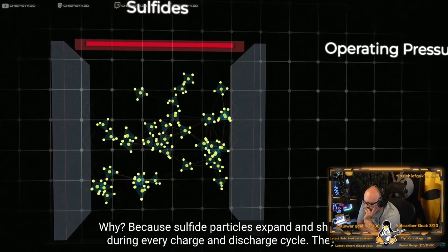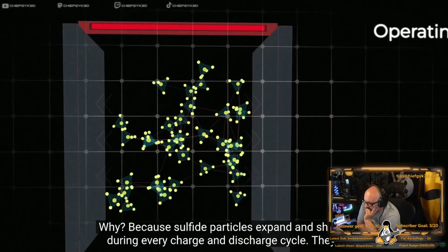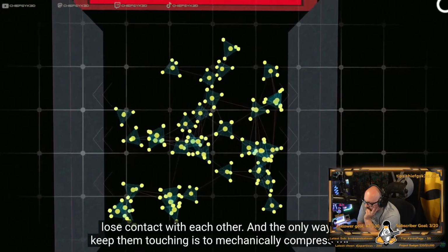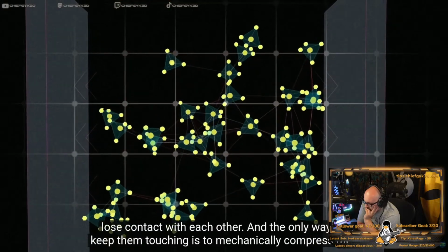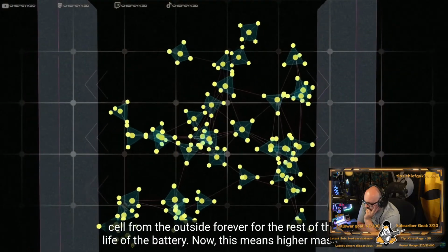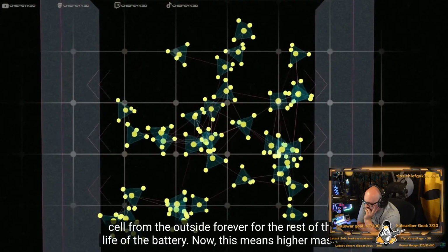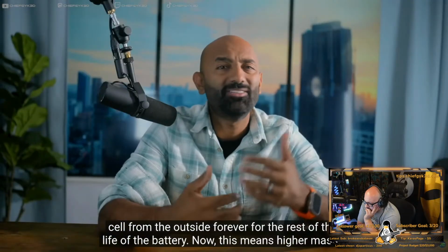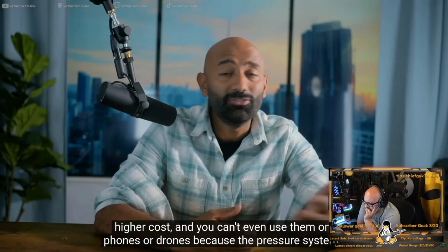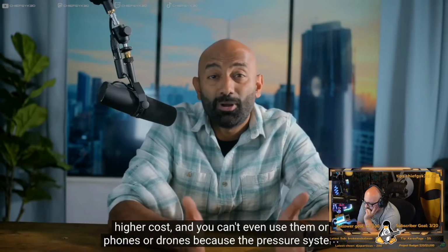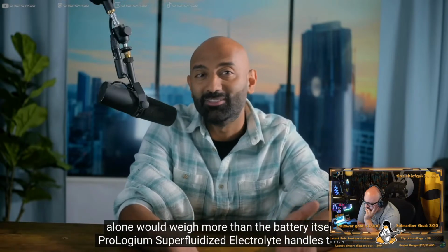Why? Because sulfide particles expand and shrink during every charge and discharge cycle. They lose contact with each other, and the only way to keep them touching is to mechanically compress the cell from the outside forever for the rest of the life of the battery. Now this means higher mass, higher cost, and you can't even use them on phones or drones because the pressure system alone would weigh more than the battery itself.